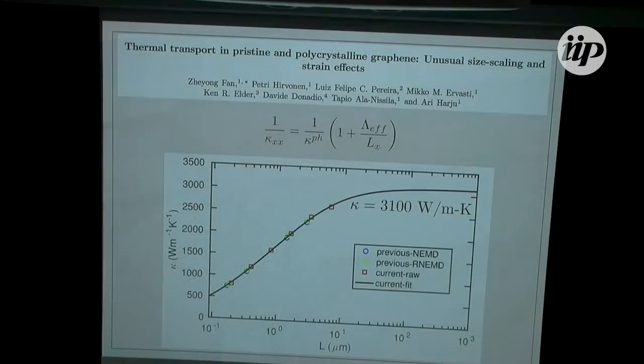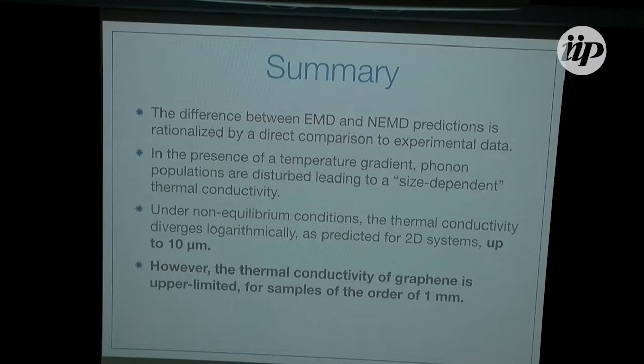In fact, just recently, we went back and got our previous MD results. So here the direct non-equilibrium and the reverse non-equilibrium. We performed new simulations, right? And we used this expression to fit the thermal conductivity as a function of length. And we see that we obtain a thermal conductivity for graphene at 300 K of about 3,100 watts per meter Kelvin. Look, this is 1,000 microns, so this is 1 millimeter, as predicted by Marzari. So in hindsight, we were right. We just didn't look for systems that were large enough.